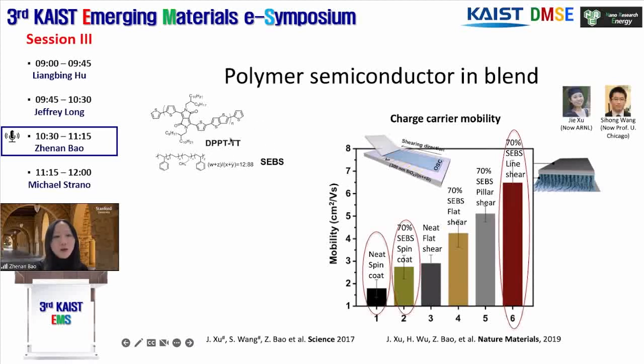So it was very surprising when we first made this blend. We noticed that compared to pure 100% semiconducting polymer, even with the addition of 70% of insulating polymer in the blend, we were able to see a doubling in the charge carrier mobility, which is completely unexpected. And then if we further control the coating conditions to control the fluid flow using this comb-like structure that we have previously been studying to control the flow pattern, we were able to further boost the charge carrier mobility of this kind of material so that the mobility now enters into the regime of that of polysilicon.